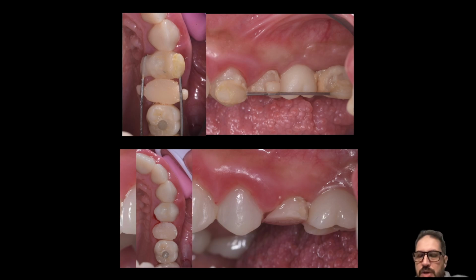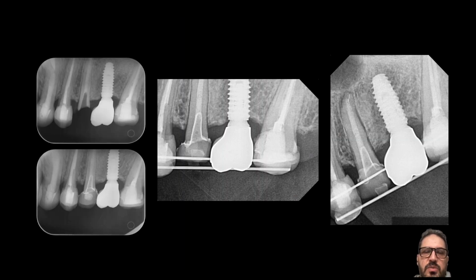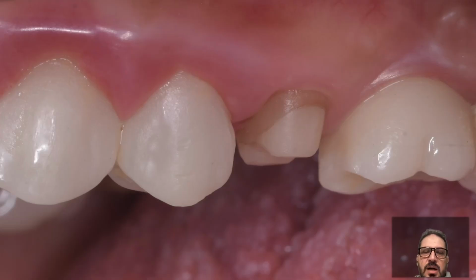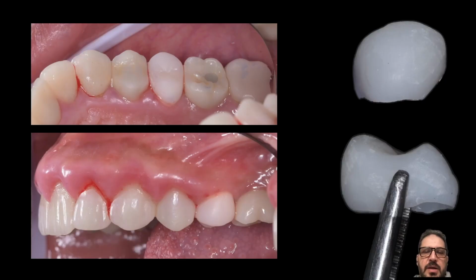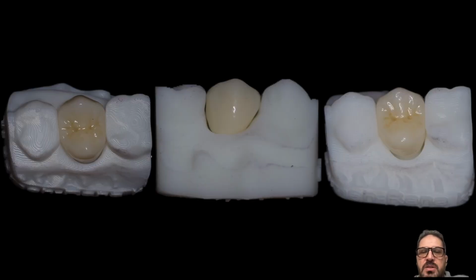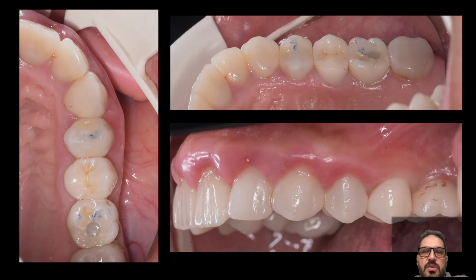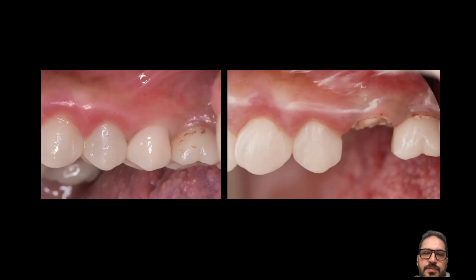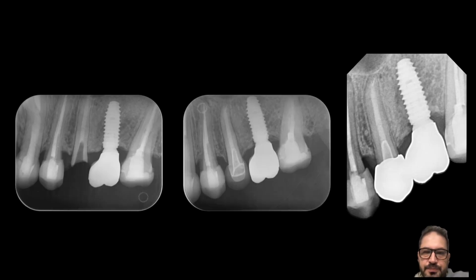After 10 days, sometimes 2 weeks at maximum, we get the maximum ferrule we want, steps in X-ray, and we get a nice ferrule, very nice ferrule. Then we make another hybrid ceramic temporary crown for tissue maturation, and after 1 month, we take the scan for the final zirconia crown. This situation, this is before. So, a 3D printed hybrid ceramic restoration in one appointment and extrusion in the same appointment, not like another technique of casted post and core, or not like a custom solution like making a stock post and composite build-up. So this is the initial situation, and this is the final situation.